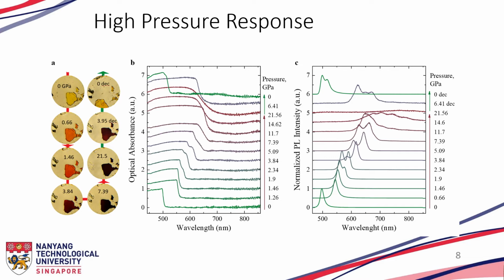It can be different phases coexisting or defects, but we will discuss the origin of the second or third components later. In general, with compression, we see redshift of the optical properties, that is first related to the change of the angle and then related to the shortening of the Pb-I bond.